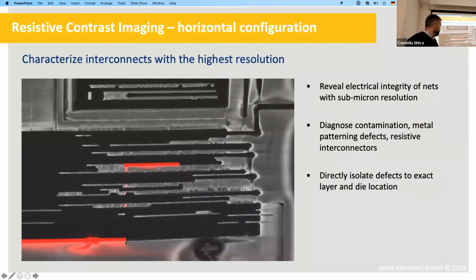And now we have colored, but it's high intensity RCI signal in red, and we have overlaid it on top of the SEM image. So we can put everything in context, and we can see that this line is coming here, it's going through a wire, it's going underneath, to a deeper metal layer, and then coming up again, and then here it's suddenly disconnected. So it's a great technique to trace things, find where the failure is, and typically from here we'll continue with cross-sectioning with FIB to look from the side to see if it's a particle, contamination, or crack. What is it that has caused that failure?